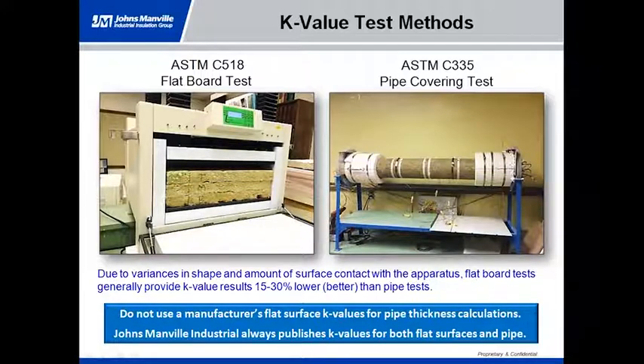so that's also going to have an impact on your results. Now, the challenge here is we're in a sense comparing flat versus round, two very different test methods. Long story short is with pipe testing, our results are typically anywhere from 15 to 30% higher than they would be for a flat test, or as we state here, your flat tests are 15 to 30% lower than a pipe test. Again, there's a big discrepancy, but C335 does probably a better job of approximating real-world situations. The C518 is a better indicator of flat performance, or maybe the material property of the material itself.